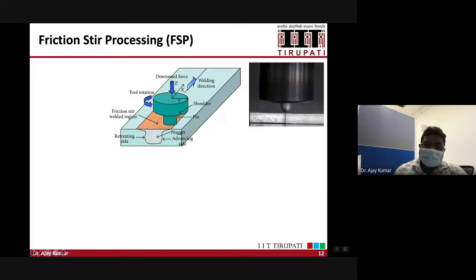Now let me introduce the friction stir processing method. You will be aware of this method very well. This method is based on friction stir welding. This is the schematic of friction stir processing, where you have the friction stir processing tool which rotates at high RPM, and then you plunge it into the material. Then it will also traverse in a particular direction. So if it is welding, then you have two metal plates, and along the welding direction, this tool will traverse. So you have the tool rotation, you have the downward force, as well as this tool will move along the processing direction or welding direction.